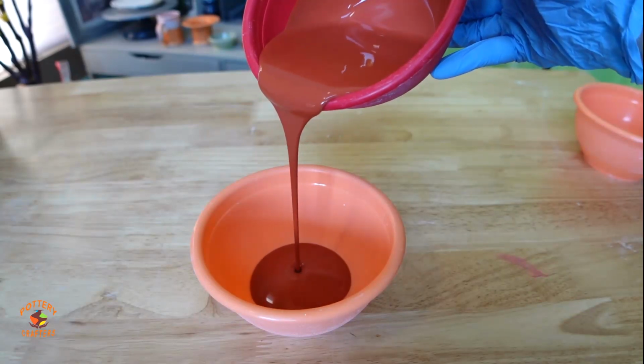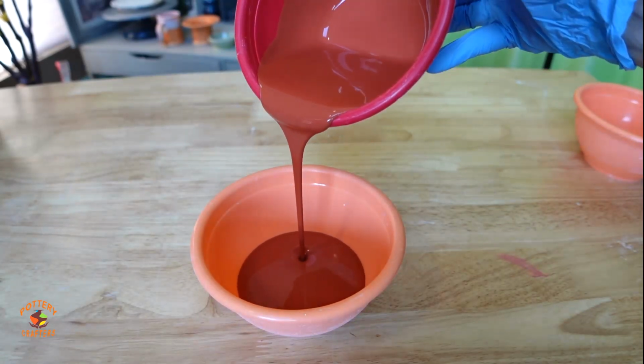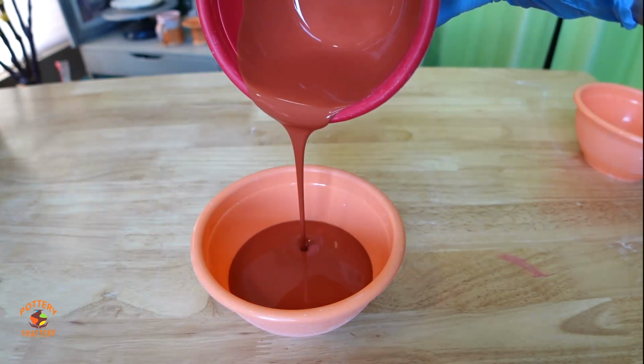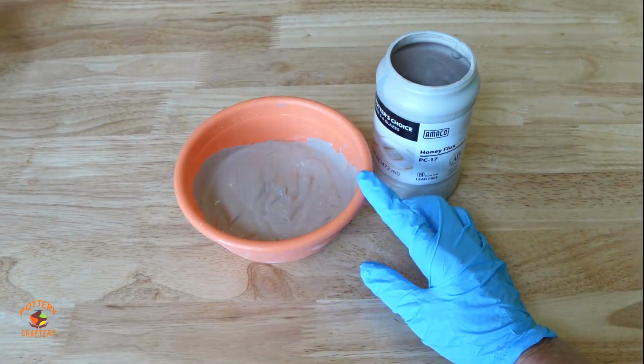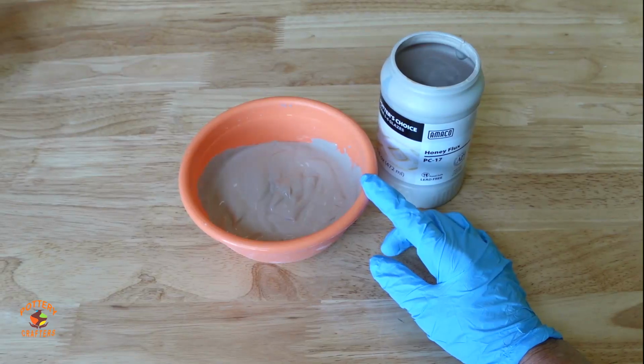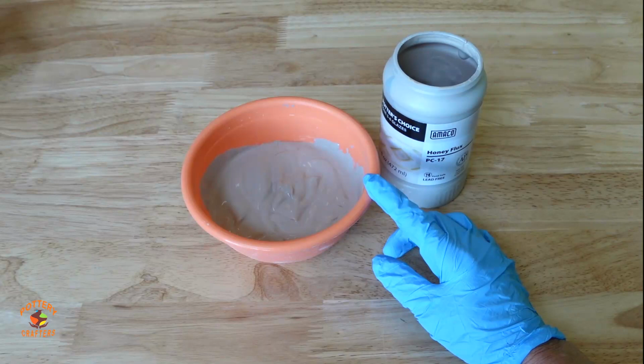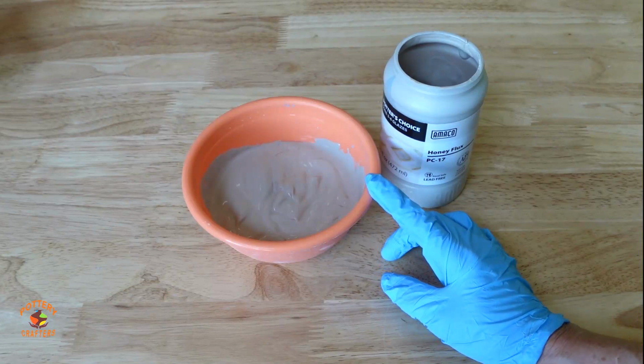When pouring on brushable glazes, the glaze should be the consistency of heavy cream, so you may have to add a tiny amount of distilled water. For the first mug, I want the Honey Flux glaze to be a little thicker because the Deep Sienna Speckle doesn't flow as much as other glazes do. So you can leave the cap off or let it sit in a bowl, as I did with this small amount of Honey Flux. You will want the consistency to be more like hot fudge.